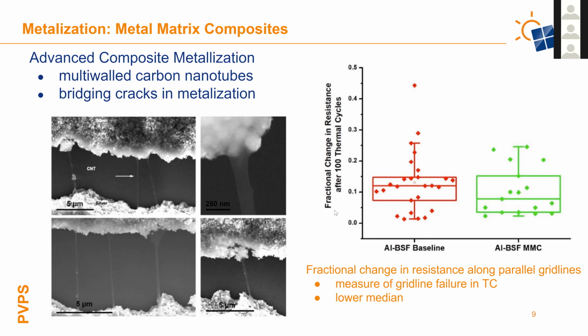This figure on the right-hand side shows the fractional change in resistance after 100 thermal cycles. What you see is the typical Al-BSF compared with Al-BSF with these metal matrix composites, and the median is much lower for the composite version. We need to look at this further at a larger scale, built into PV modules, but this might be a way to mitigate these small cracks in our metallization.